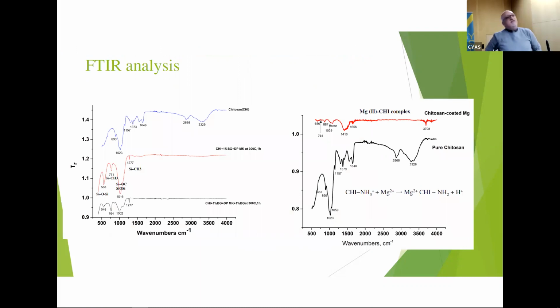We did FTIR to get information about the link we have after coating, and that gives an indication. For example, that's a little bit easier, this one. That's the pure chitosan we are using. After conversion coating with magnesium, they form a complex. That means some kind of reaction has happened between magnesium and pure chitosan. So that gives indications here that some kind of change has happened in our coating structure.